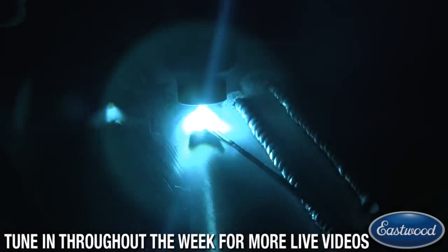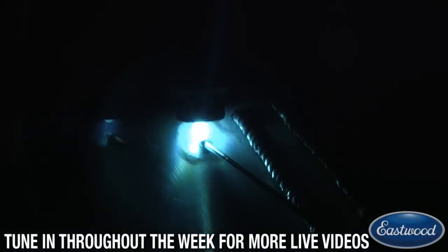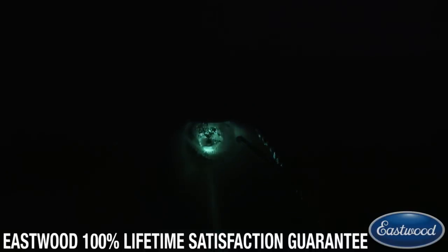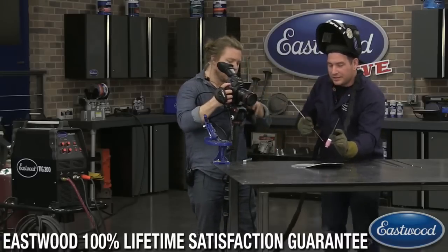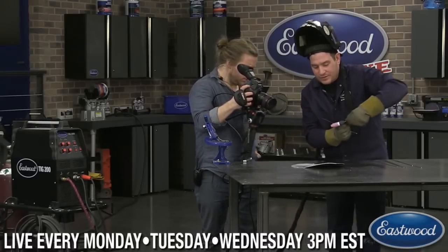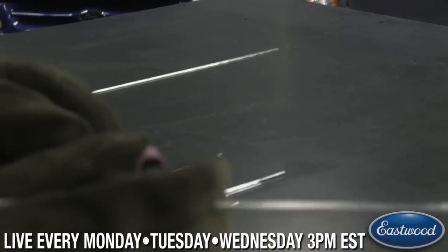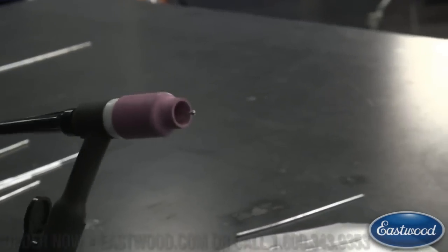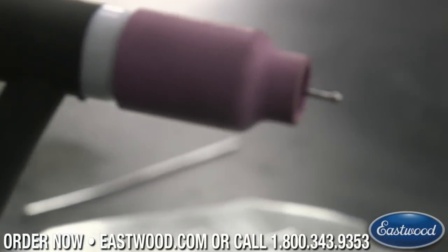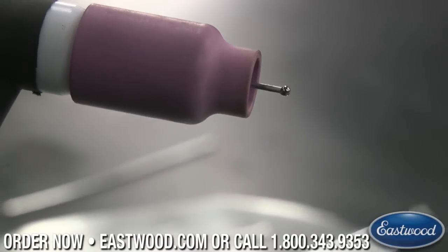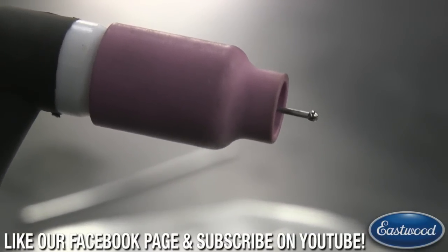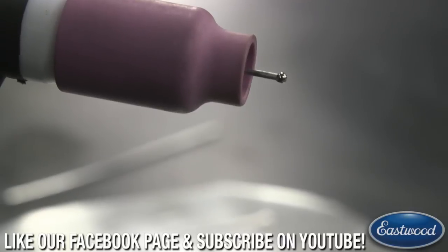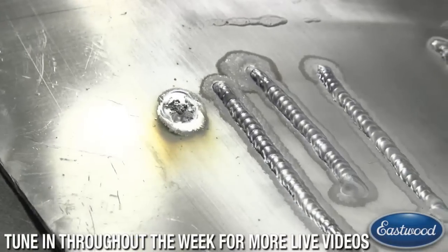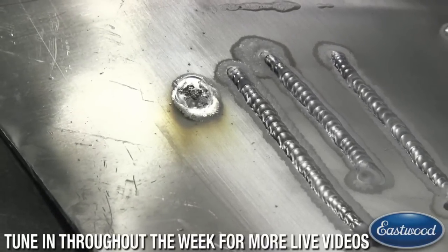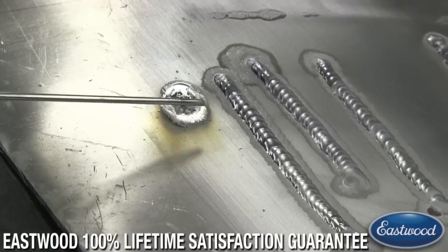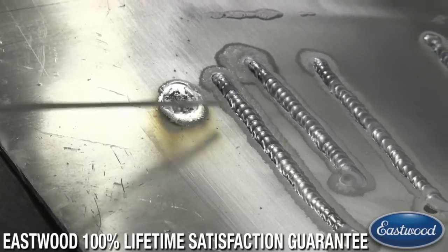See what's happening? It's actually burning the electrode away, and I can't even get a puddle to form. I'm going to give up already. What's happening there is it's putting the heat all into your torch, into the tungsten. It actually burned off part of the electrode of the tungsten, and it started burning back. So we'll show you the tip of the electrode here. This balled up, and what it was doing was burning back. I actually had to pull this back out to show you guys, but it burned back into the torch. It also dropped a piece of the tungsten into the weld and immediately contaminated this weld. So you can see all this junk here in the weld, and we got that residue around, and we just couldn't get it to actually start an arc.